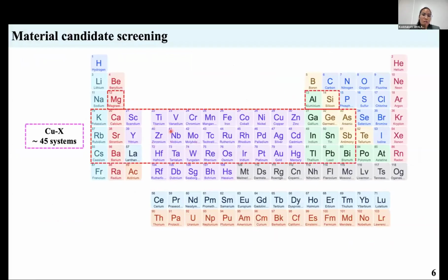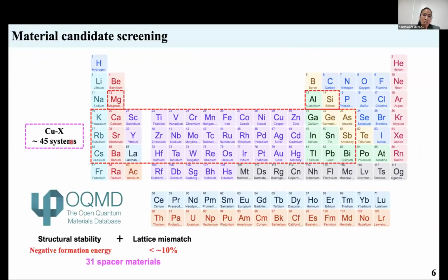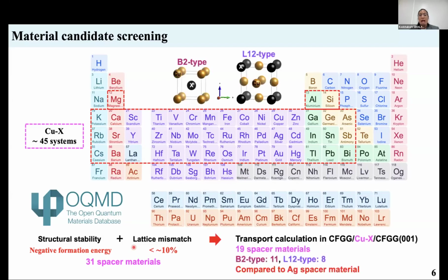For the material candidate screening process, we focus on elements within the rectangular region, as shown here, which includes 45 Cu-X alloy systems. For the initial screening of materials, we use the Open Quantum Materials Database to select the systems based on their stability, as indicated by negative formation energy, and the lattice mismatch with the CPP-GMR electrodes less than 10%. So out of 45 systems, 31 meet these criteria. However, today I would like to share my results of the transport calculation for 19 spacer materials with B2 type and L1_2 type structure, and we will compare our calculation results with the Ag spacer materials.